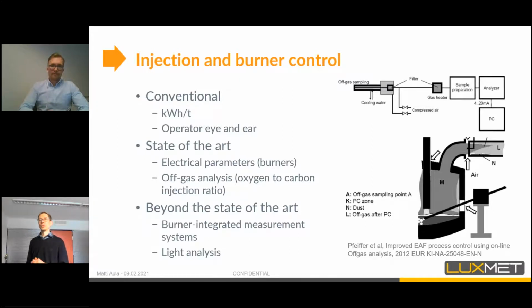But there are also other methods to do this. For example, we can use electrical parameters, such as THD, meaning the arc stability, to estimate this. If our arc stability is already high, we know that we are close to flat bath, then of course we should not use the burners again.